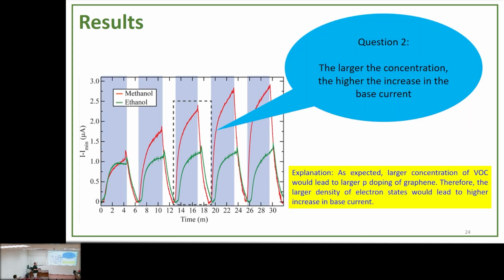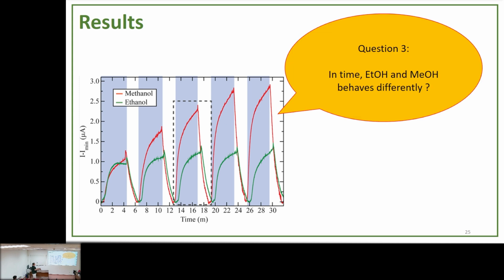Then question 2. The larger the concentration, the higher the increase in the base current. We see it, and actually it's something expected. As expected, a larger concentration of organic compounds would lead to a larger P-type doping of graphene. Larger P-type doping means a larger concentration of charge carriers, so you can expect this increase in current. But you see, it's not increasing that much. It's the third question. In time, it seems that ethanol and methanol behave in different ways. Why for ethanol am I not having such an increase? Instead of this increase, I'm having almost saturation with ethanol.